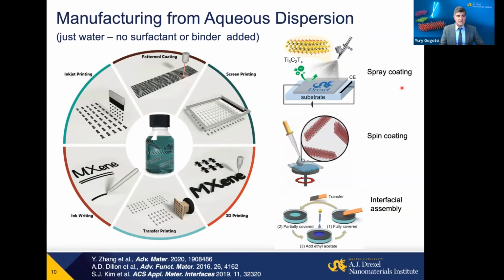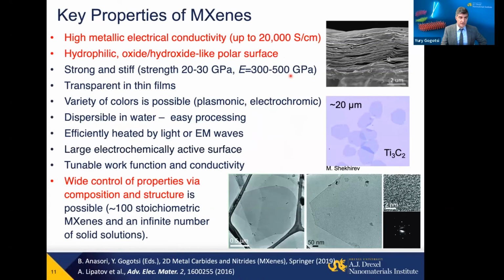What is important, we don't need any surfactant, unlike, say, for graphene, carbon nanotubes, metal nanowires, nanoparticles, or binders. Dispersion will happen because of high negative charge on the surface. And after that, also these functional groups help MXene particles to stick to each other strongly here.